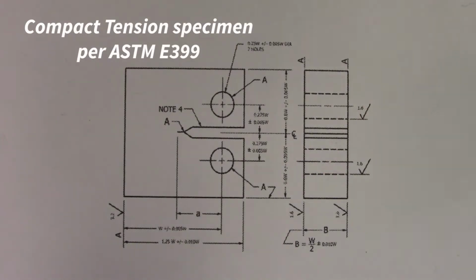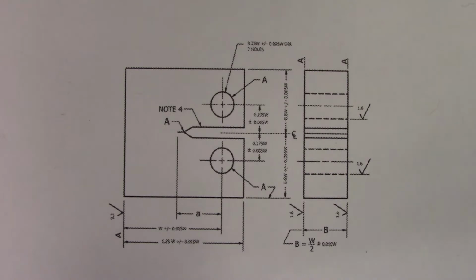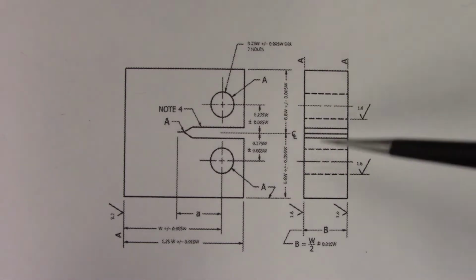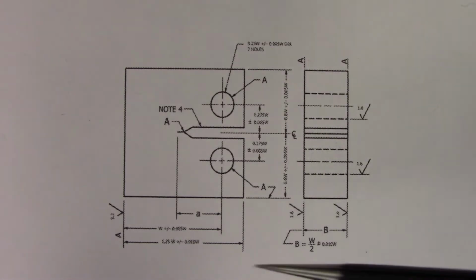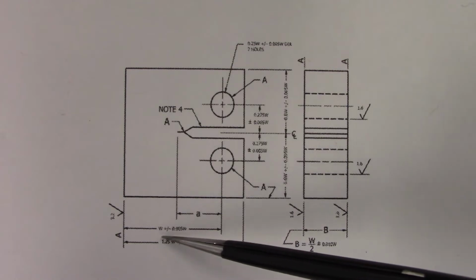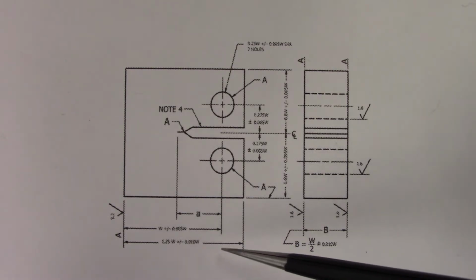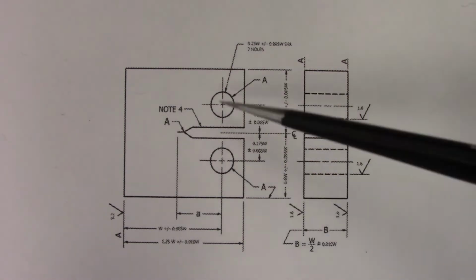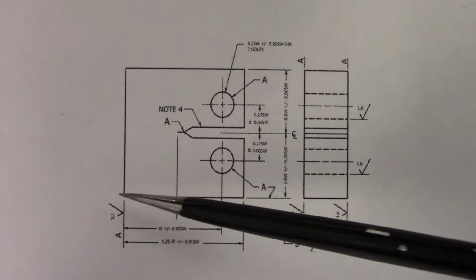So here's the schematic of the compact tension specimen as specified in ASTM E399. If you notice, most of these dimensions scale according to the W dimension, this dimension here. That dimension is measured from the center line of the loading holes to the back of the specimen.